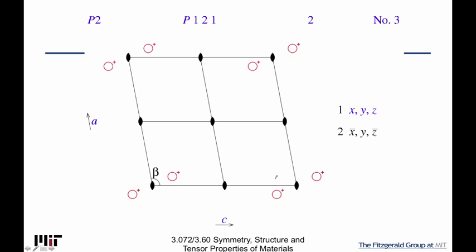Now getting a little more complicated. You can see the change in notation — we call this P2, where we took the primitive lattice and just added a twofold axis. This is going to be 3D, so this is just adding a twofold axis to the monoclinic. We shifted from triclinic to monoclinic, because a twofold axis can only be compatible with the monoclinic system.